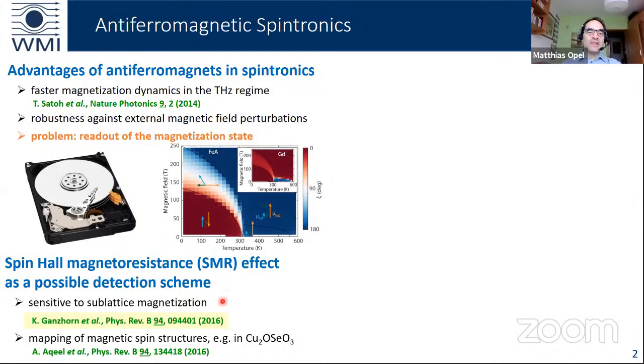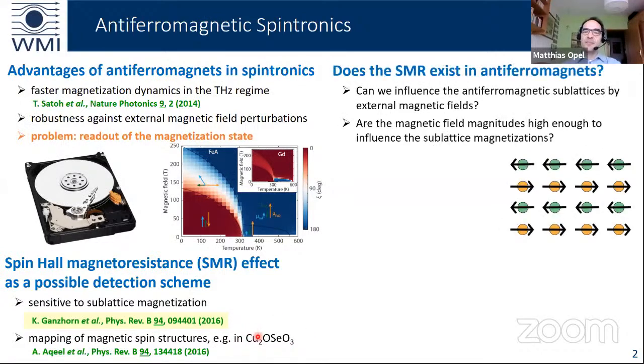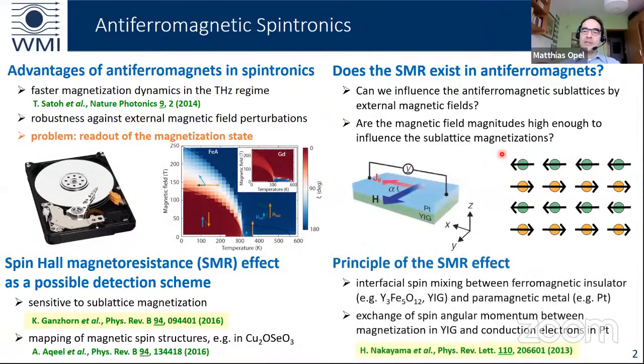We were able to show that the spin Hall magnetoresistance is sensitive to the sublattice magnetizations and that it allows us to map the magnetic spin structure, for instance, in helical or chiral magnets like Cu2OSeO3. The problem with antiferromagnets is, does the spin Hall magnetoresistance effect also exist there? Can we influence the antiferromagnetic sublattices by external magnetic fields? Are the magnetic field magnitudes that we achieve in our labs high enough to influence these sublattice magnetizations?